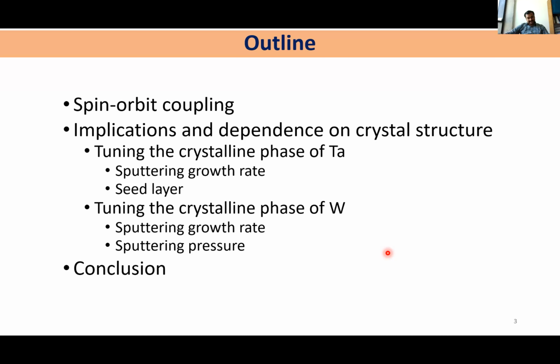One is how to tune the crystalline phase of tantalum via sputtering growth rate, and also by using different thicknesses of a seed layer, basically a crystalline seed layer such as nickel iron. And then I'll discuss how to tune the crystalline phase of tungsten via sputtering growth rate and sputtering pressure. I'll show you the implications of changing this crystalline phase on the spin Hall angle via spin pumping and inverse spin Hall effect measurements.